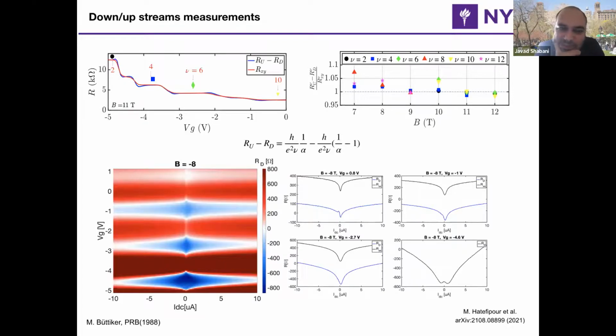You can also do bias measurement. I saw in one of the YouTube talks that there was some very interesting bias dependence. In our system, we have done it, and we don't observe anything drastic, in the sense that when you do the bias on the lower graph, let's just look at the lower left, basically the negative resistance obviously disappears. It goes towards 0, right? At high biases. These are DC biases now. And I have made cuts on the right-hand side of that and compared it also to RXX. So you see that RXX shows these dips, and the blue line also follows that. When you basically kill quantum Hall, then these dips also disappear. So basically this negative value is also tied up to the strength of the quantum Hall in the system.